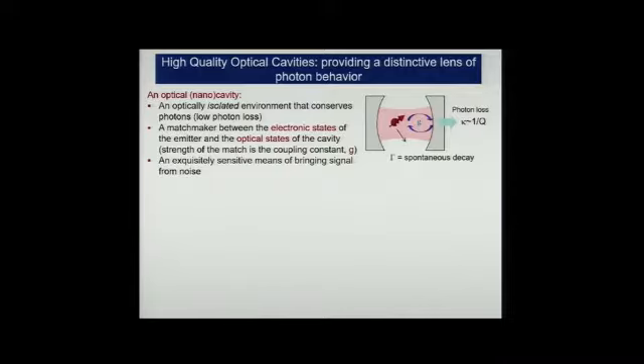But as indicated here, the optical cavity is not a passive protective environment by itself. It is an environment that we have uniquely engineered to populate with discrete, finite photon states. So our geometry gives us particular photon states, and we try and engineer the photon states so that they're resonant with the electronic states of the emitter or the defect within the cavity. And in fact, the cavity and the emitter interact with each other in an intimate way, so that the electronic transitions of the emitter, that energy interacts with photon states in the cavity. The photon states in the cavity have a certain lifetime, go back and interact with the emitter.